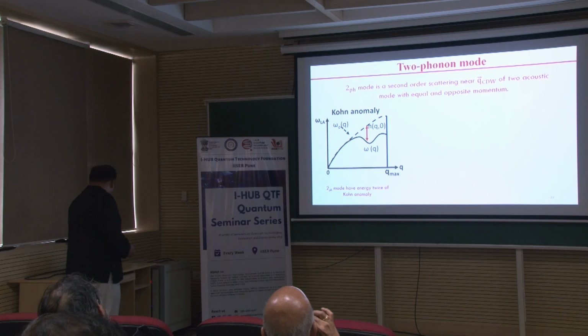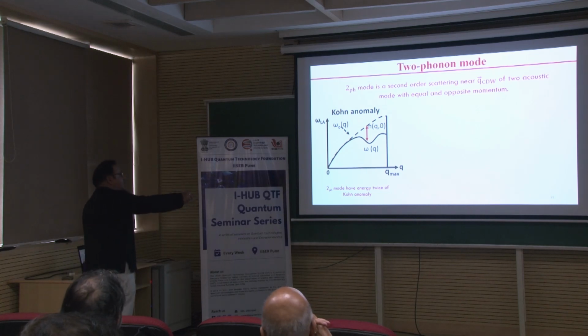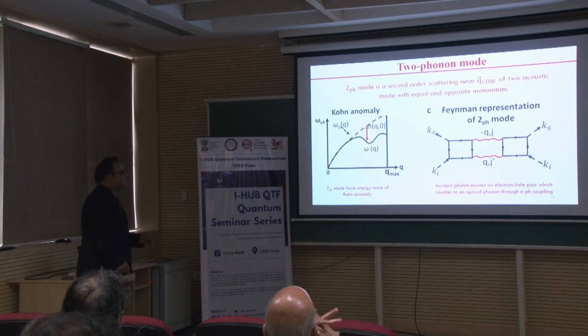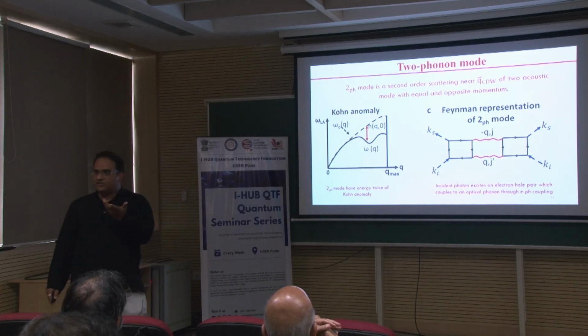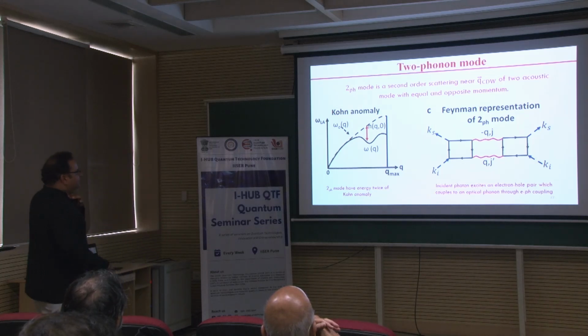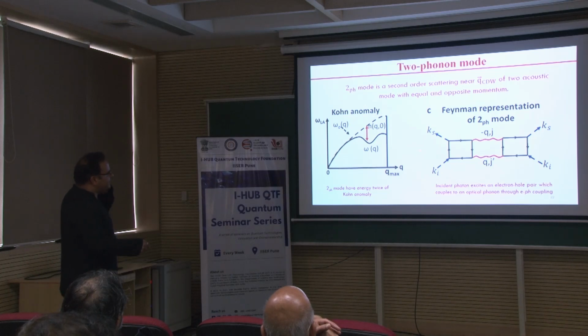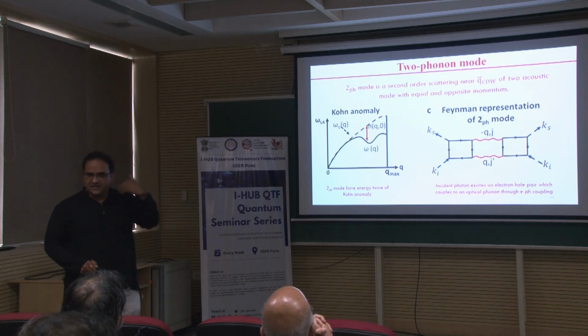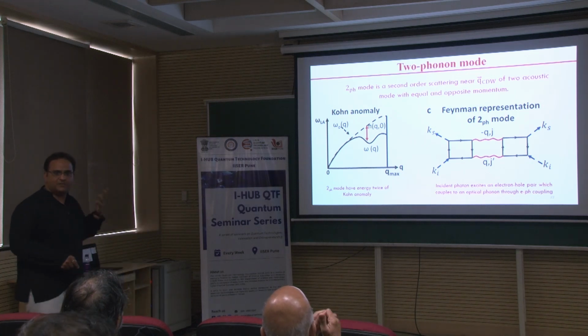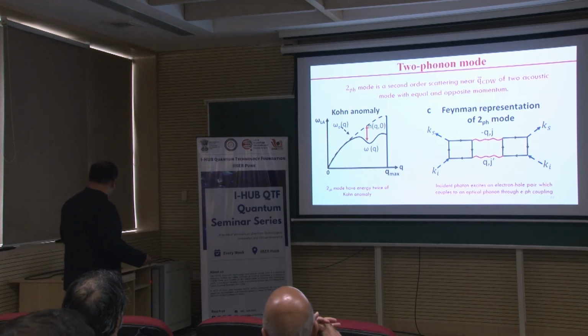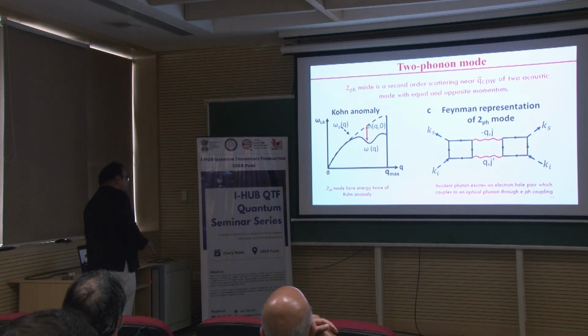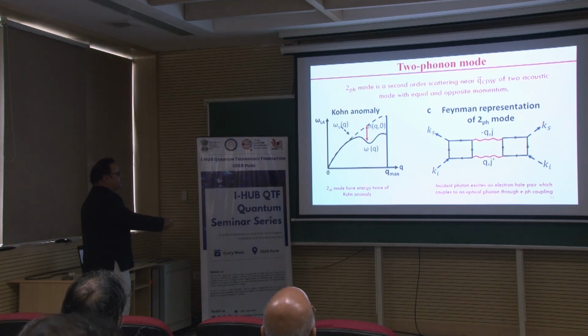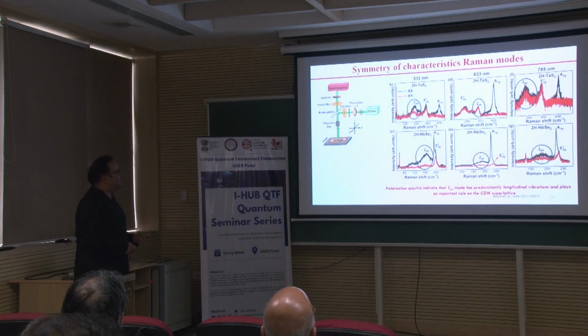Now, this is associated with the acoustic mode, but when you talk about observation in Raman spectra, you talk about the optical mode. So what is happening here is that you have an incident wave and a scattered wave interacting with the lattice, so you have electron phonon coupling. That electron phonon coupling actually stabilizes or conserves the total energy in these instabilities as well. This 2 phonon mode has the energy which is twice that of the Kohn anomaly. What is the symmetry of that?